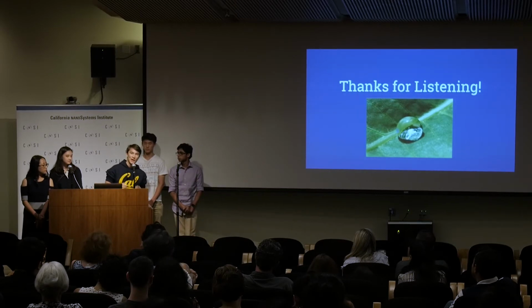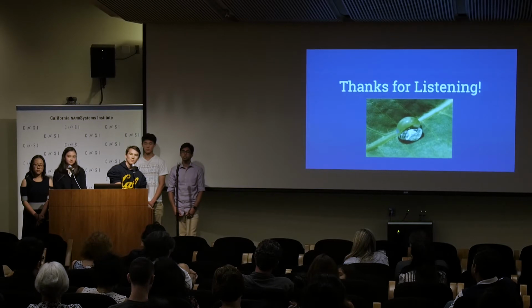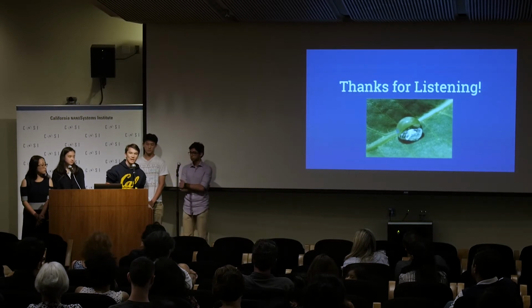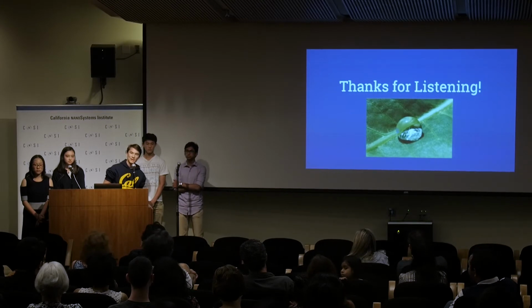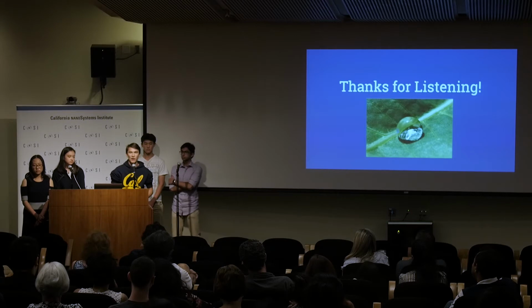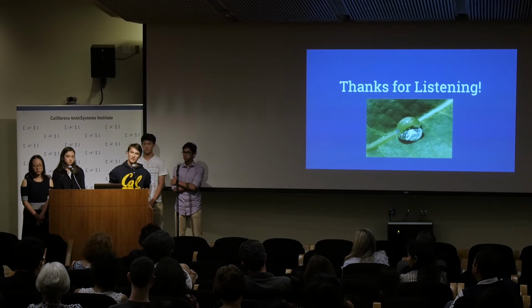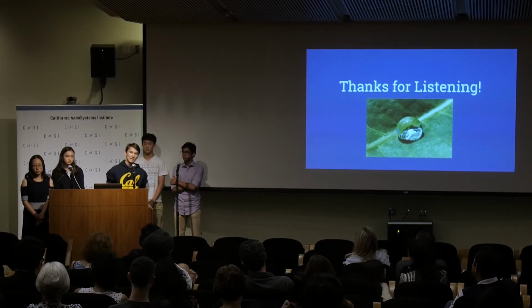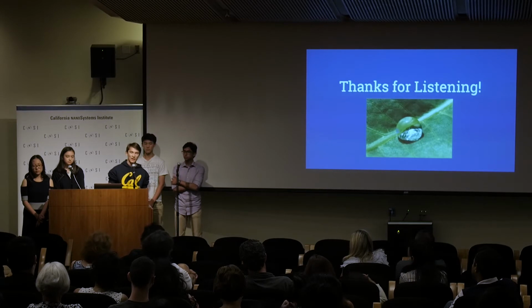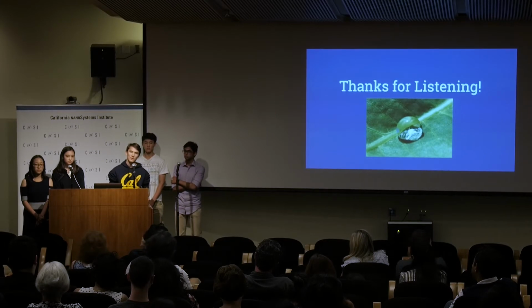So are you wondering how nanoscience was applied into this? We actually tried another experiment, just soaking it in the hydrophobic coatings like DCT or lecithin, with just sanding the copper, not putting the nano rough silver particles in it. And we found really no noticeable difference in the contact angle between regularly sanded copper and the sanded copper soaked in DCT or lecithin. So it really highlighted how important the silver nanoparticle structures on the micro rough surfaces were in order to make a surface hydrophobic.